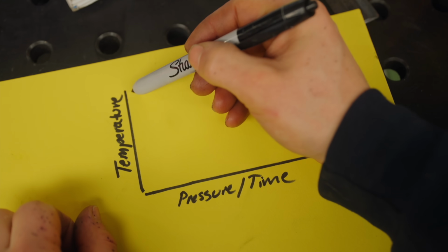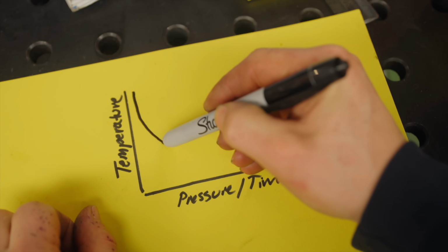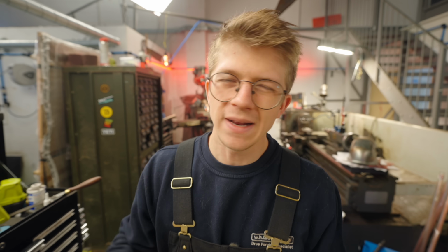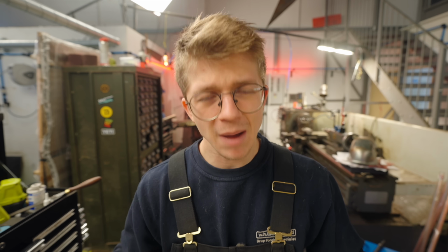We know that we can get stuff to stick with high temperature, requiring less pressure and time. We know this because we can heat up steel white hot, just touch it together and it'll stick. But when it's 850 degrees Celsius, we've got to beat the crap out of it with the steam hammer.